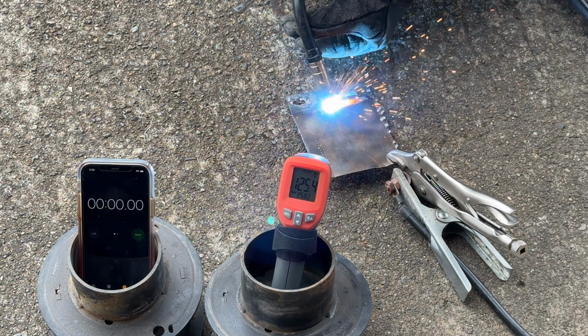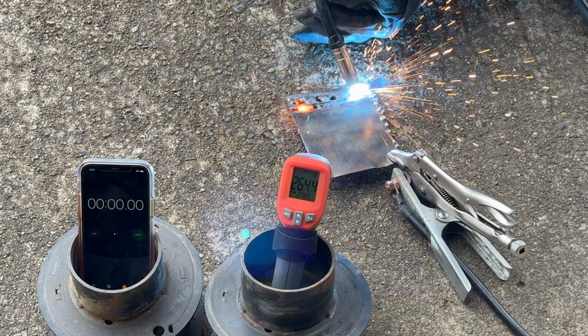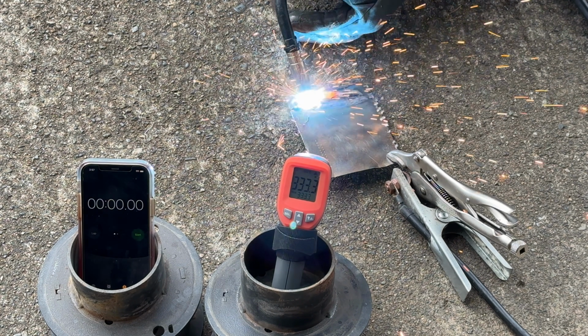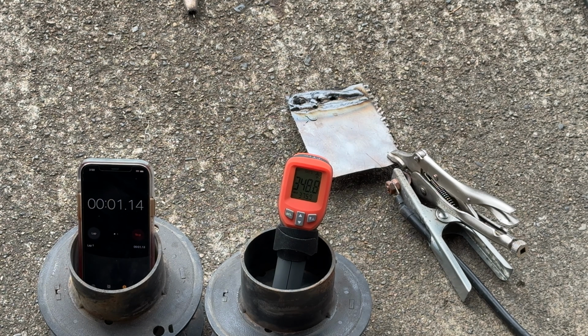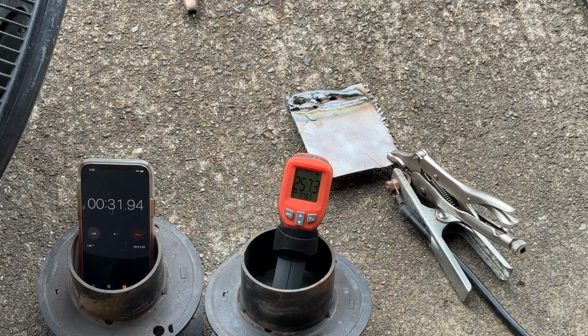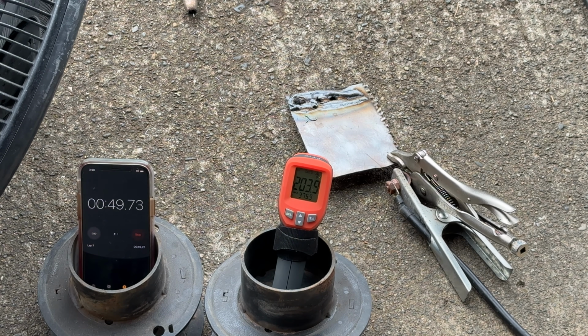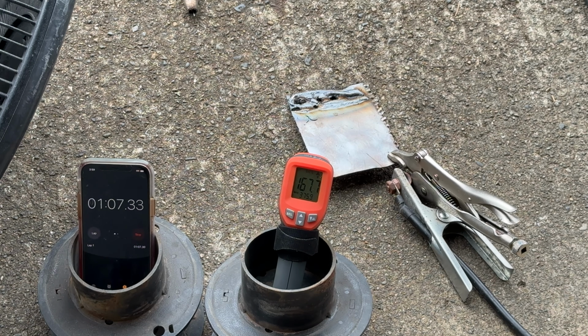Then I repeated the test, and this time around I was able to get my temperatures up almost 100 degrees higher. And once I started the timer, I set up a fan to the left of the test panel, and with it going on full blast, I wanted to see just how much quicker this panel would cool down with that bit of help.